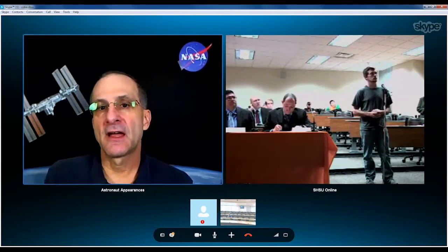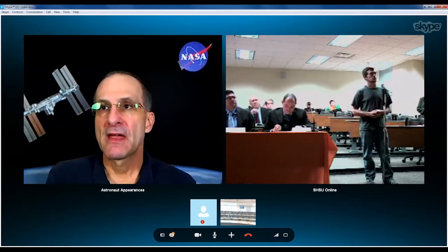If you look at using this on Earth, if you're doing it in a vacuum furnace, by virtue of pumping the furnace down into a vacuum, you're going to drive most of the moisture off. And then after you start heating it, you're going to drive even more of the moisture off. So if this is a high temperature operation, I don't think there's going to be much moisture around. If you figure out a way to cure this at a much lower temperature that maybe you could use for windshield repair, then you might have to worry about moisture being there.